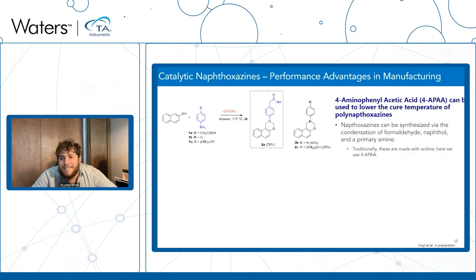Naphthoxazine resins are really cool materials because naphthoxazines can often possess a higher glass transition temperature than the cure temperature of their material. And typically we make naphthoxazine resins by taking something like naphthol and condensing it with aniline to make a naphthoxazine, which you see here on the far right labeled 2B. You apply heat to this material, it ring opens across that strained cyclic middle part of the thing.